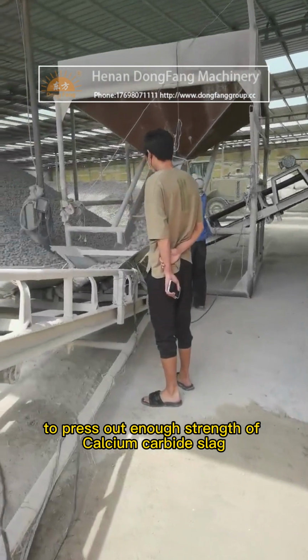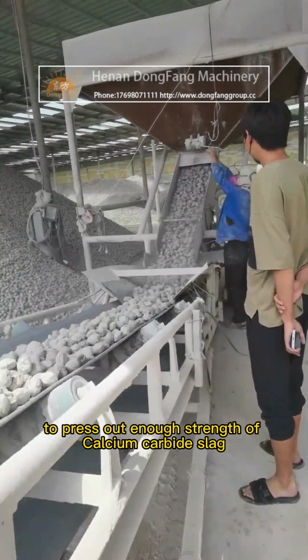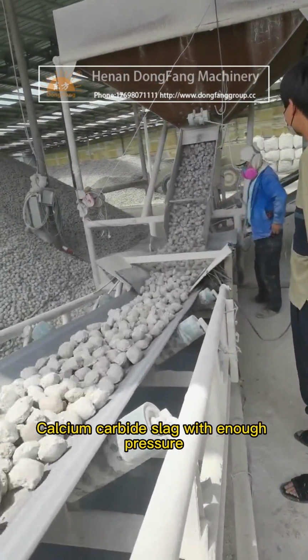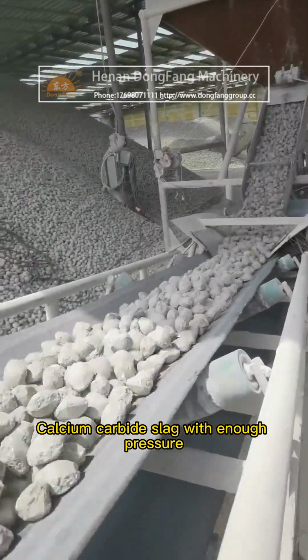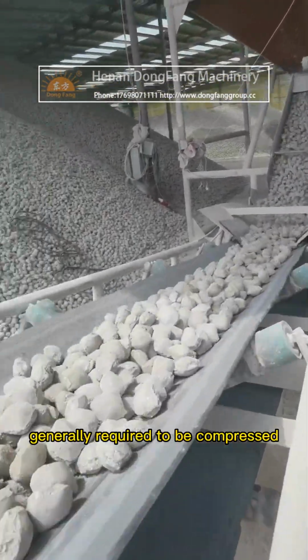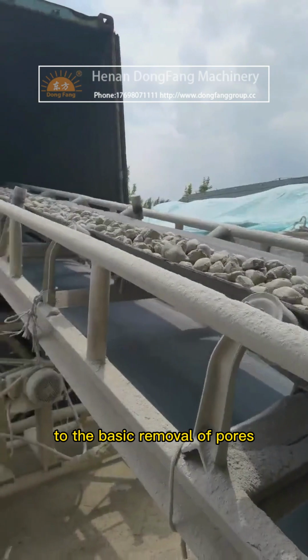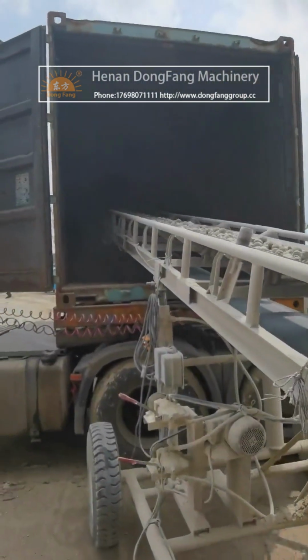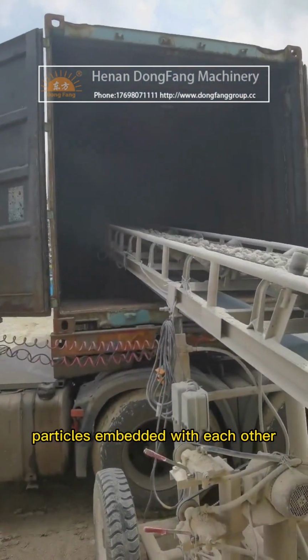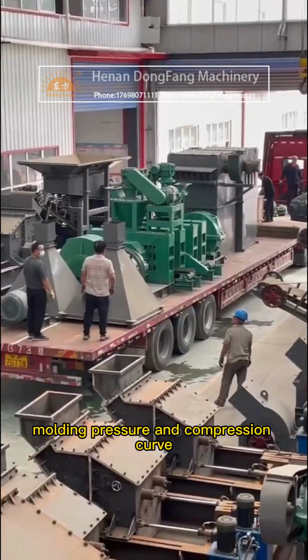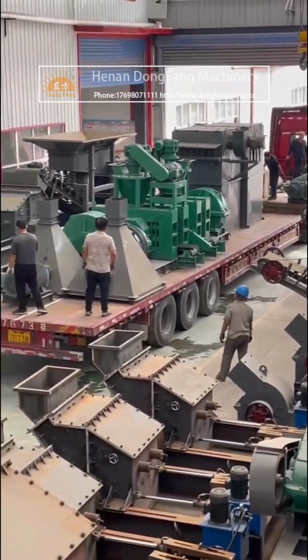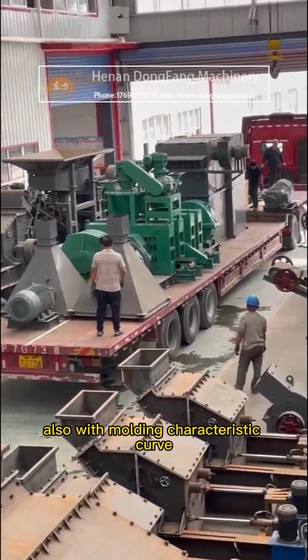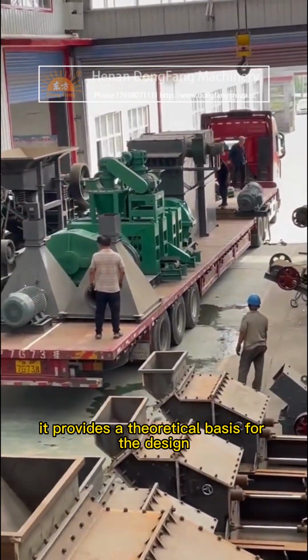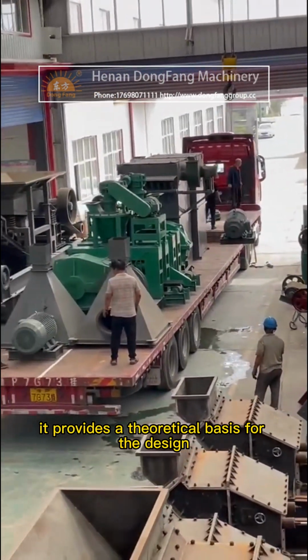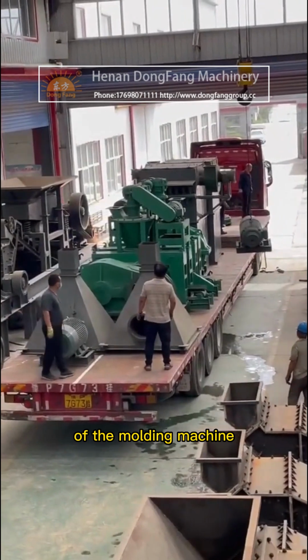To press out enough strength of calcium carbide slag with enough pressure, it is generally required to be compressed to the basic removal of pores, with particles embedded with each other. The molding pressure and compression curve, also the molding characteristic curve, provide a theoretical basis for the design of the molding machine.